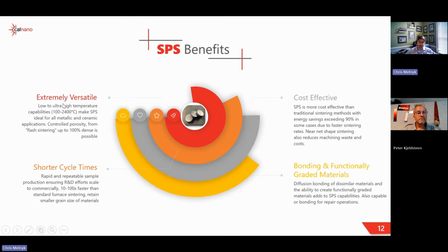We can put thermal gradients in on purpose. If you're doing a monolithic component, you would want temperature uniformity, and of course we have ways of achieving that. If you wanted to make what would be called a functionally graded part, where you have, say, a ceramic on one side and a metal on the other, even if you have to do that in multiple layers that are all bonded together, you might desire a higher temperature and a lower temperature from one part of your component to the next. And that can be designed in SPS because we have current density to play with, so we can design asymmetrical tooling, which would get hotter in one area than in another, which is another advantage. You can't do that in a hot press necessarily, because that's pretty difficult.